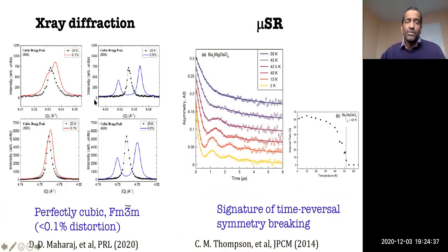This comes partly to Shubhro's question, which is that if, for instance, there was a higher transition where something analogous to this quadrupolar ordering was happening in the system, then you would have expected to see some change in the structure. Admittedly, in examples where we know them, these are actually quite weak. And so one has to do fairly high resolution X-ray diffraction experiments.